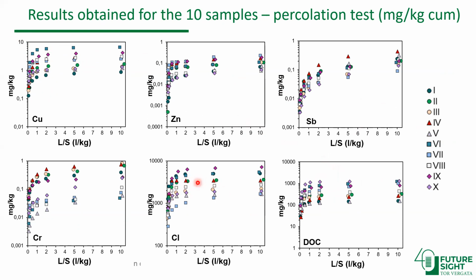For chlorides, generally the finer fractions tend to release more, as you can see here. And the same we can also observe for antimony and chromium over time. Here, the liquid to solid ratio. Now, looking at the results of a pH dependence test, here we plot the concentration of each element measured in the leachate as a function of pH.